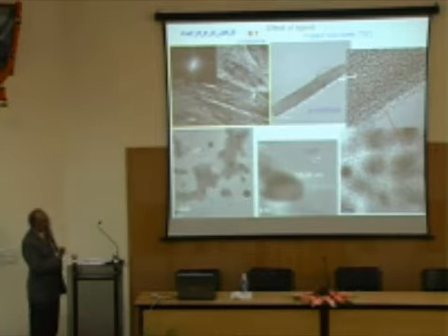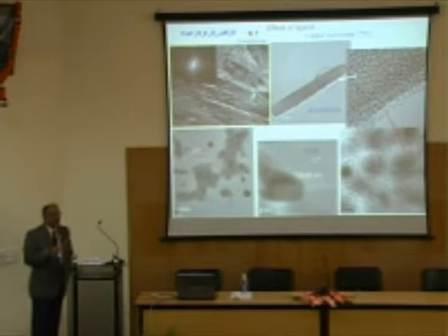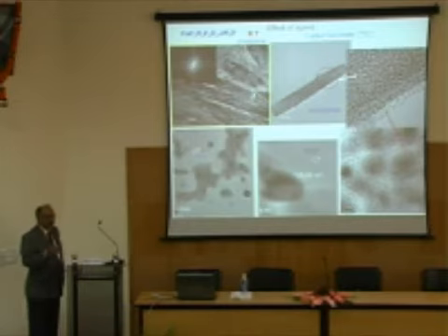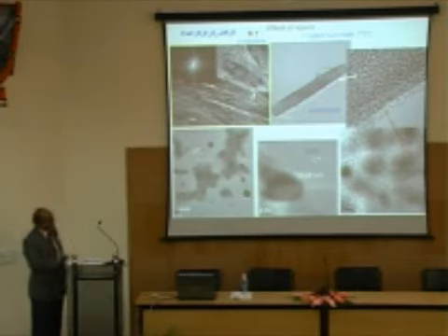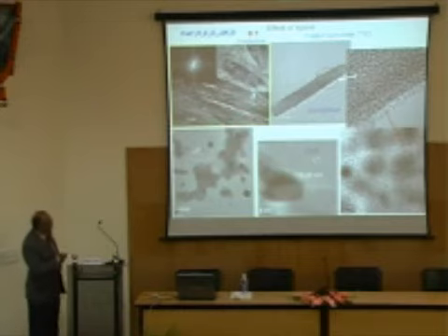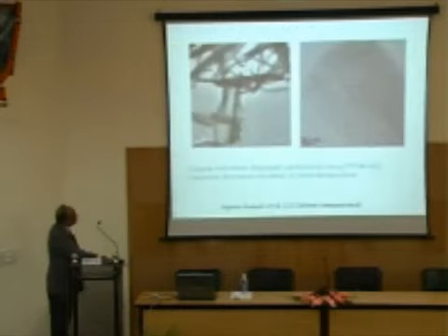So it's called amorphous. So we can control the crystallinity of the rods, and as you know, the crystallinity affects the properties of the material. For example, crystalline silicon is very different in properties, the band gap is different, than amorphous silicon, right. So all materials, depending on the crystallinity, the properties will be different. So we can control these things by doing certain changes.